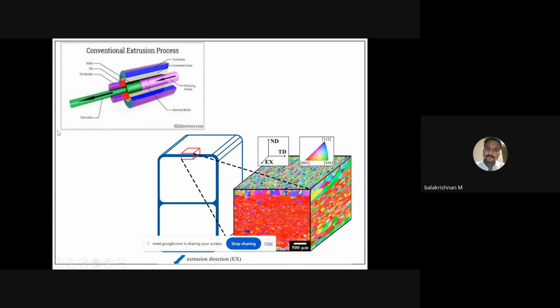While we go for the extrusion process, this is a sample area of extruded parts. Here we can see the plane normal to the direction, the transverse direction, and the extruded direction. Here is the cut section of the portions, and we can observe the formation.